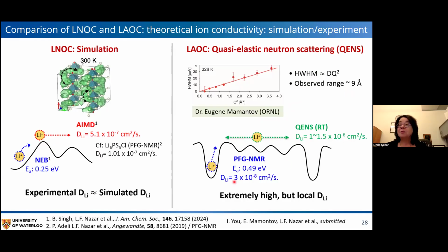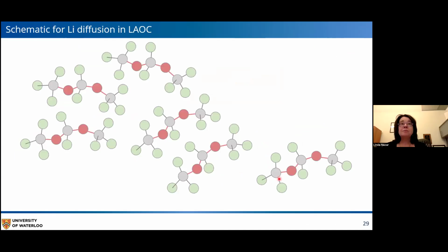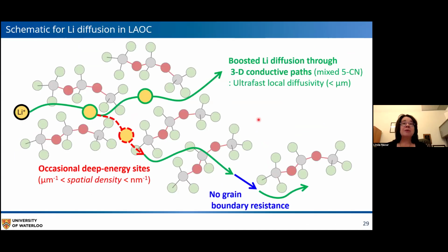But the PFG NMR shows that we have slower diffusion on the long range. So we have local high mobility, but a long range diffusion coefficient a little bit slower certainly than the oxychloride, but not slow by any means. So then we can come up with a sort of scheme for diffusion in this material where we have these 5 coordinate type centers, boosted lithium diffusion through these paths, pretty good diffusivity. We have these deep trap states, which unfortunately in the long range slow things down a little bit, but of course no grain boundary resistance because it's an amorphous glassy material.